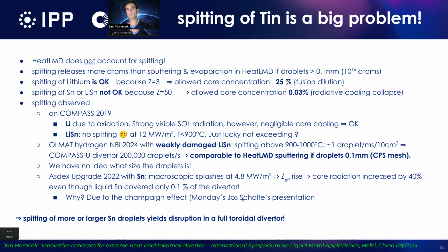We probably know now why this happens. This was Jos Scholte, 2 papers published on this. It's probably the champagne effect. The hydrogen just bubbles out from the tin. And this is something which would be probably quite difficult to avoid. So far, nobody figured out how to avoid this. So tin seems to be quite dangerous for tokamaks.